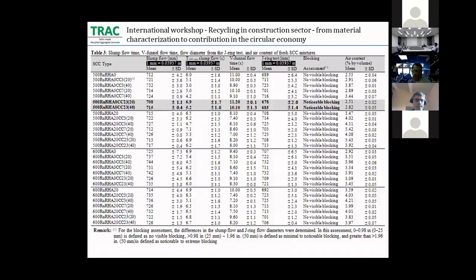For the properties in the fresh state, filling ability: as you see, a slump flow of self-compacting concrete in the range of 725 millimeters diameter is generally accepted in Europe, because a slump flow below 700 millimeters diameter has the potential to segregate the cement paste and aggregate. Table 3 summarizes the slump flow time to reach 500 millimeters diameter, V-funnel flow time, flow diameter from the J-ring test, and air content of fresh self-compacting concrete mixtures.